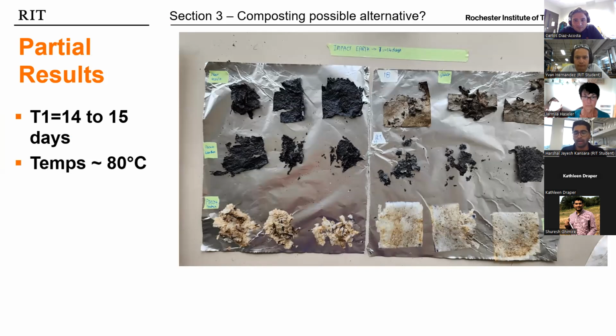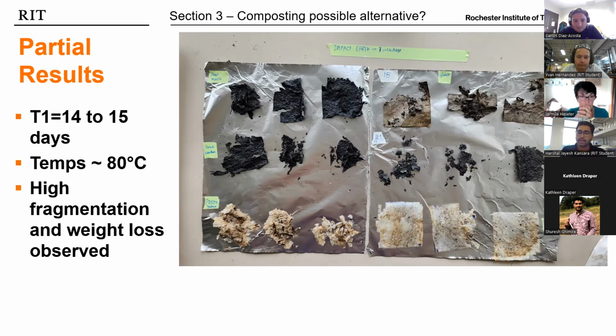I haven't shown it here yet, but at the second time point, T2, about 25 to 30 days, the fragmentation is even more. So the results seem extremely promising. The temperatures we have seen in the compost are about 160 to 180 Fahrenheit. We have seen as high as 70 to 80 Celsius in the compost initially, and very high relative humidity too. Very high fragmentation was observed, as I mentioned, and the second time point is looking even more promising, with 25 to 30 days of material breakdown.